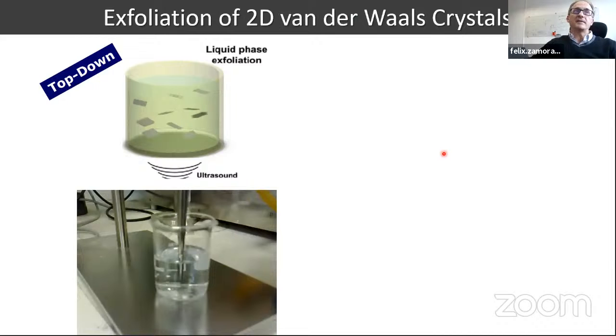You can also do exfoliation starting with the same precursors, the same 2D van der Waals crystals, but doing what we call liquid phase exfoliation. For that, you start with the crystals. You can use small crystals in this case. You don't have to use these big pieces of crystals as in the case of micromechanical delamination. Then you have to adjust a lot of experimental parameters. Just to simplify, you have to look for a proper solvent or mixture of solvents, and then a kind of energy source. Probably the most typical one is ultrasound.